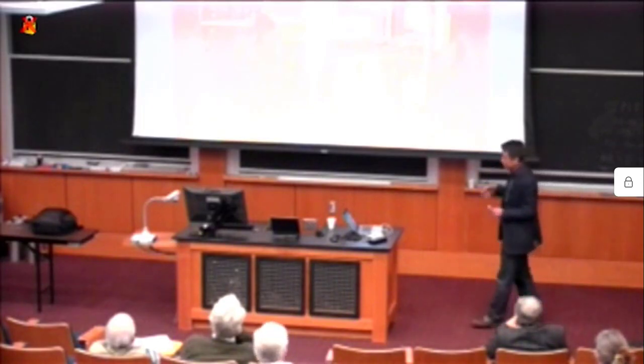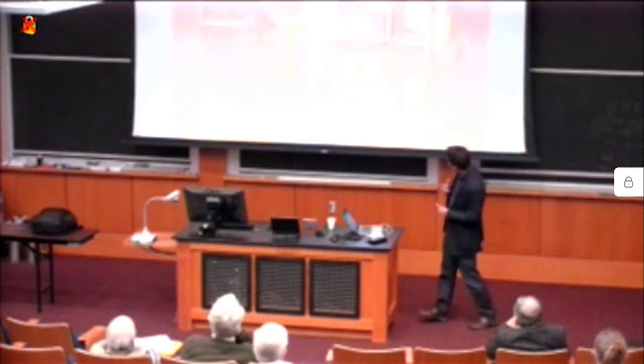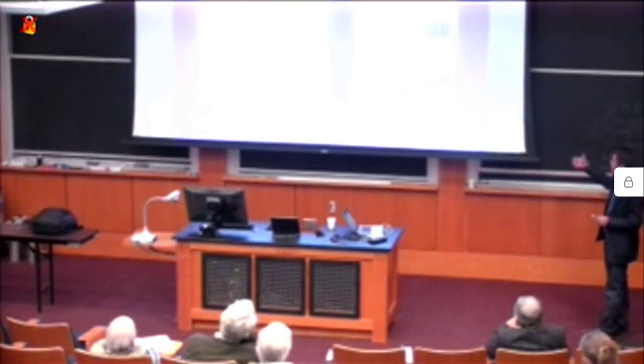I know this is not really a material-centric audience, but I just give you a brief picture of the types of things that we're doing. We're using an ultra-high vacuum version of pulsed laser deposition. And so we're taking a UV laser pulse to evaporate a physical plume and deposit this very slowly and carefully on a substrate hanging upside down over here. And the key experimental technique, whether you do this by molecular beam epitaxy, laser ablation like we are, or sputtering, is that you really need to be able to see in real time and monitor these sorts of structures on an atomic scale, and that indeed is possible.